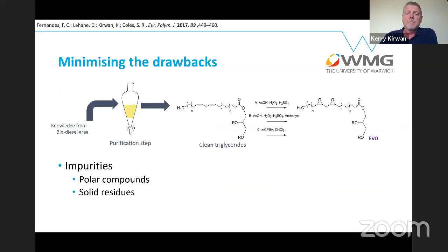Now, a few years ago, we did a lot of work with biodiesel and looking at second generation fuels. So again, vegetable oils, and we learned a lot about how we could remove the polar compounds and the solid residues and take it back to something that chemically looked very, very clean. So we had a clean source of triglycerides. In that instance, we were mixing it with methanol and glycerin and making biodiesel, or a form of biodiesel. In this instance, what we were doing is mixing it with other chemicals and catalysts and turning it into an epoxidized vegetable oil.